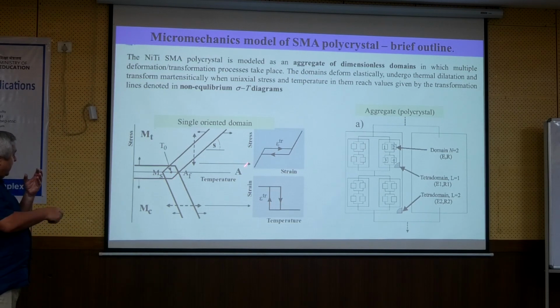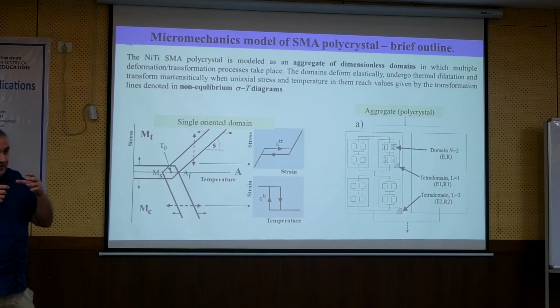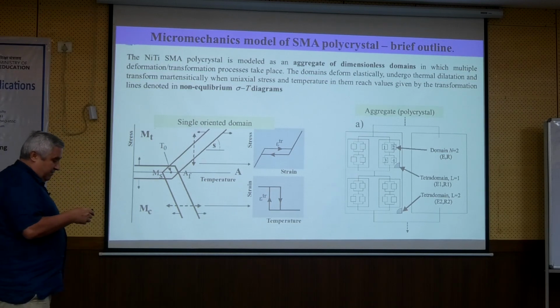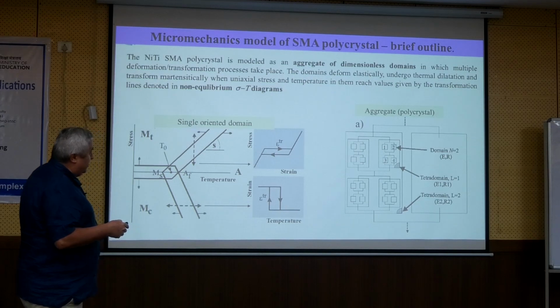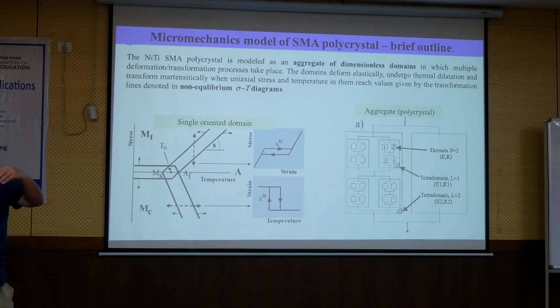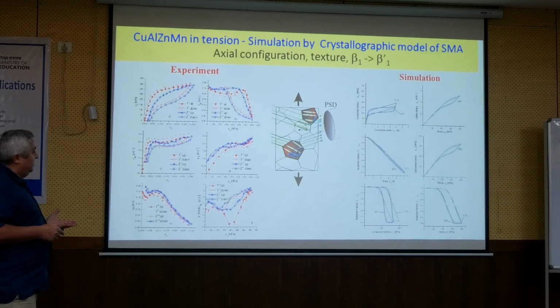So for each domain, I know these responses. Even if it's the bar and it has some texture, so most of the orientations are 1-1-1 oriented, I can impose the texture on such kind of aggregate. So we came with this type of model, which actually combined our knowledge about the anisotropy related with Martensitic transformation in copper-based alloys, and try to develop the model which would simulate the aggregate, meaning the polycrystal. And the result was surprisingly good.